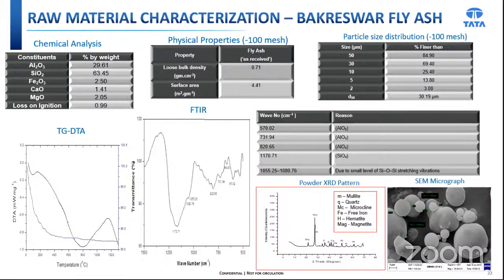DTA and TG curves indicate very little loss through a continuous endothermic reaction. The initial loss is due to the removal of absorbed water in the sample. A major loss is because of the unburnt carbon present in the fly ash, whether from a thermal power plant or another plant. This unburnt carbon comes out.